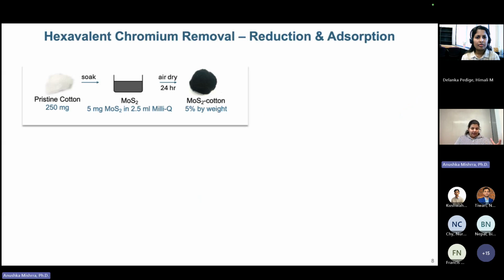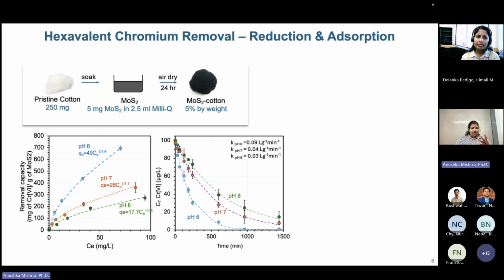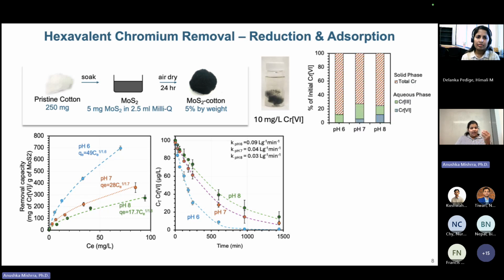So once we prepared this, we did some studies using batch experiments. So like you can see the small vial over here, we have the cotton suspended in it. It's just like any other wool. And we had a lot of chromium that we loaded onto it so that we can see the effects in a larger scale. So we ran with 10 milligrams per liter of chromium-6.